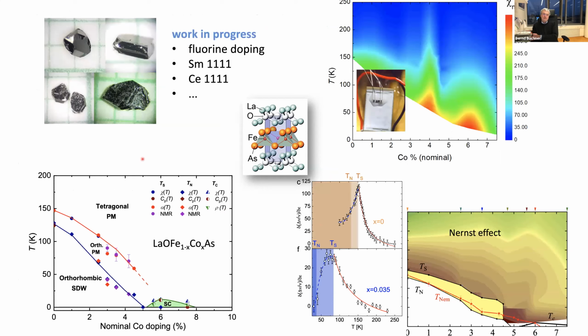So I've presented you some first results on this first series of single crystals. It's still work in progress. We try to get the fluorine doping working. We now also have systems with higher TC. I've shown you this kind of phase diagram. I've shown you this very prominent, very pronounced double peak feature, which you see in the nematic susceptibility, somehow inferring that indeed nematic susceptibility is strongly coupled to superconductivity here, and it is coupled to spin fluctuations, which leads to very strange behavior in the normal state of these materials.